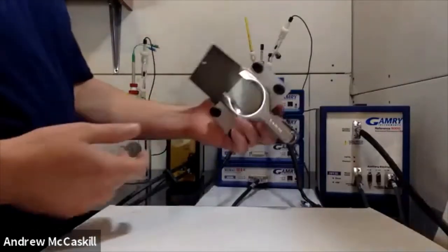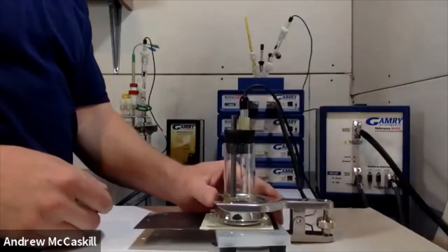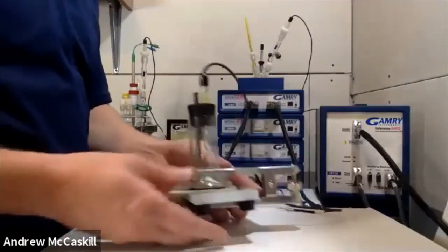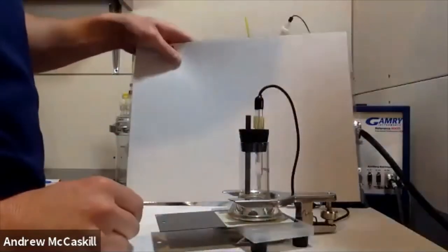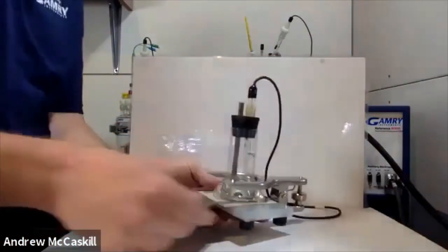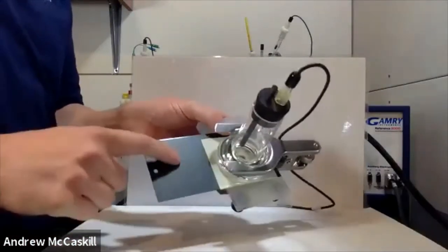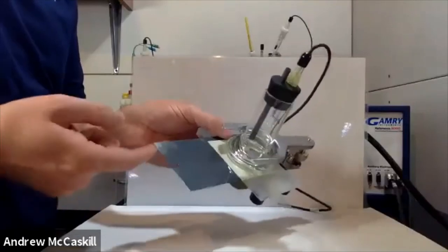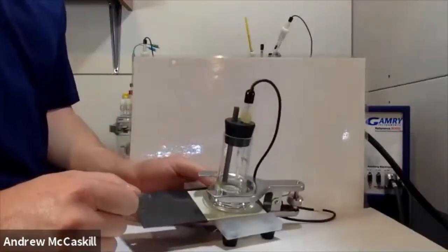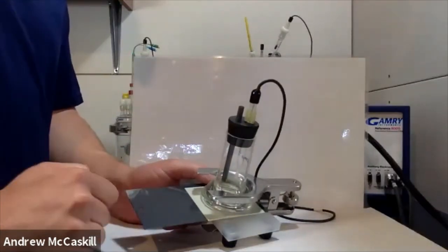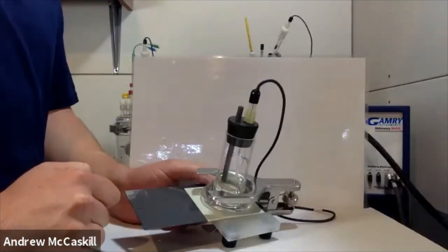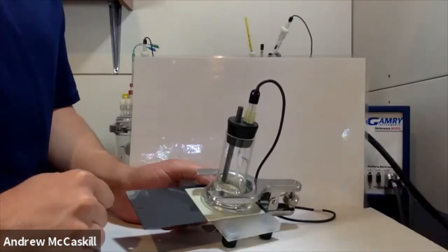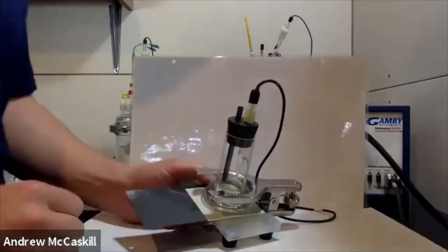So the first cell that I wanted to show, it's one of my favorites, it's probably one of our most elegant cells. It's actually the paint test cell here, PTC1. And this cell, let me put this behind here to kind of isolate what we're looking at a little bit. So busy back there. So this cell is primarily designed for testing coated samples. And you can see right here, I have a coated sample. I scratched off some of the surface to expose the metal beneath. Running electrochemical experiments on coated samples can be a fast and effective way to characterize the coating as opposed to doing long exposure experiments and just doing maybe a weight loss or visually inspecting the coating after weeks of testing. So this is a faster way that you can test coatings.